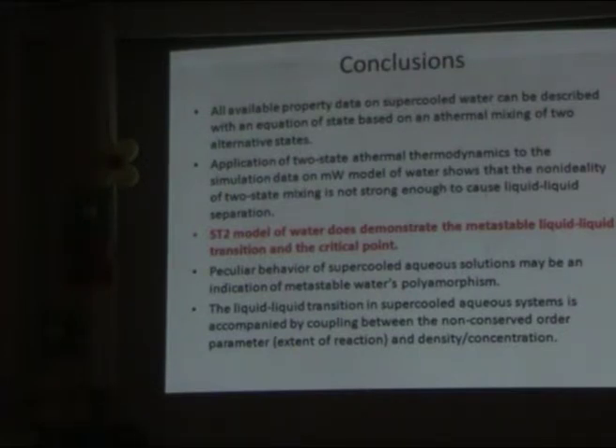The ST2 model of water definitely demonstrates the existence of a metastable liquid-liquid transition and the critical point and is beautifully described by our thermodynamics. Peculiar behavior of supercooled aqueous solutions may be an indication, maybe, I must be very careful in wording, of metastable water's polymorphism, because the solution could be ideal. There is no reason to phase separate the solution of sodium chloride unless this phase transition originates from the liquid transition.